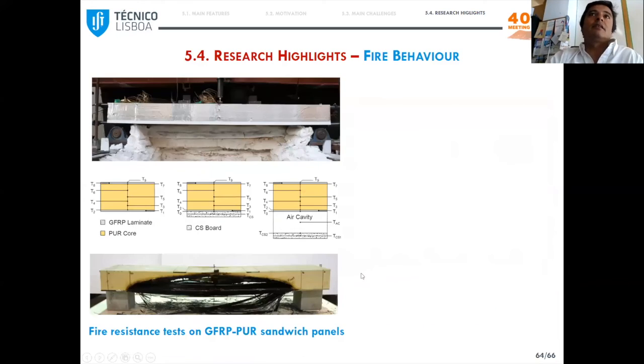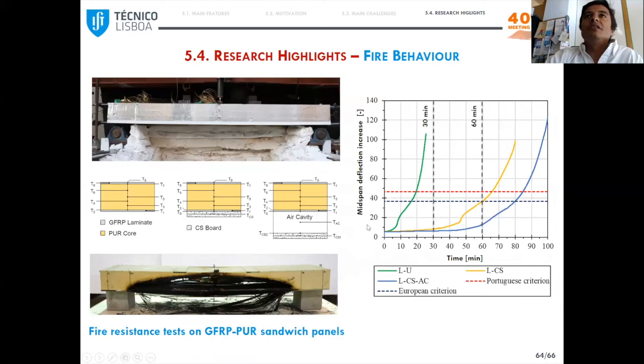And then the fire resistance behavior of sandwich panels without any protection and with board protections, either adherent or with an air cavity. Here you can see a panel after being tested for fire. And here you can see in this plot the mid-span deflection increase as a function of exposure to fire time. Without any protection, the resistance was lower than 30 minutes. And with these two protections, it was possible to exceed the 60 minutes of fire resistance.